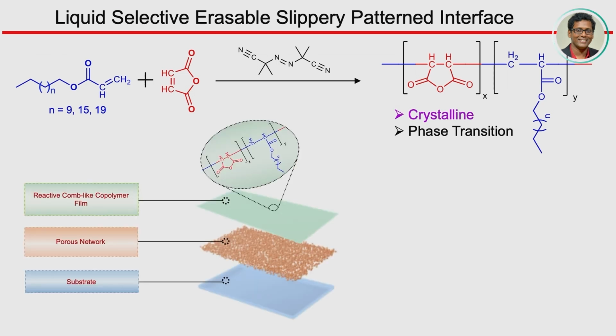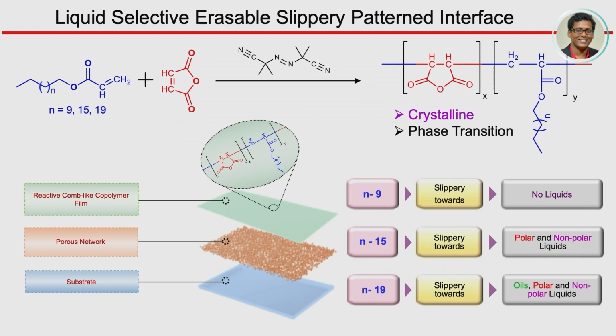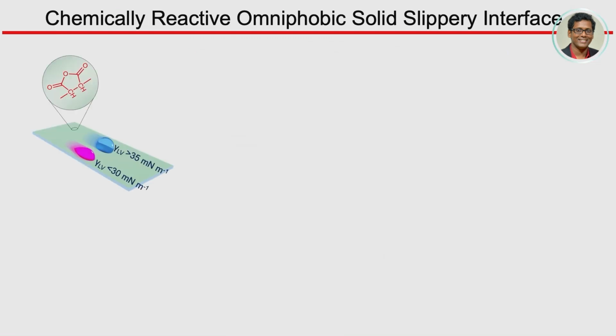You can see we have a substrate, and we can develop this porous network, which is our bread and butter that we regularly do in our lab, and then infuse this copolymer inside the porous polymeric coating. Once you have that, depending on the category of this long-tail hydrocarbon, you can have a sliding property towards polar or non-polar liquids. If you have anything less than that, you don't have any sliding property, and if the hydrocarbon tail length is around 19, then it will slide even oils. Sliding oil is always a difficult job, but that can also be achieved. That's the way you can come up with this omniphobic solid slippery coating.